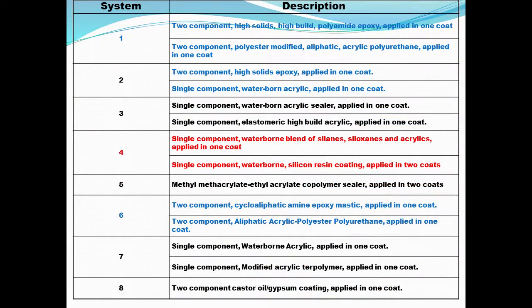We looked at 8 coatings. I put coating system number 4 in red simply because it was applied in the field, not applied in the lab, because the supplier for that coating, once we had obtained it and began to do our work, insisted that that was a 24-hour cure between the prime and the second coat. And that was one of the criteria we had initially established; we didn't realize that his coating needed that, and we didn't want something that necessitated a minimum of a 24-hour cure.